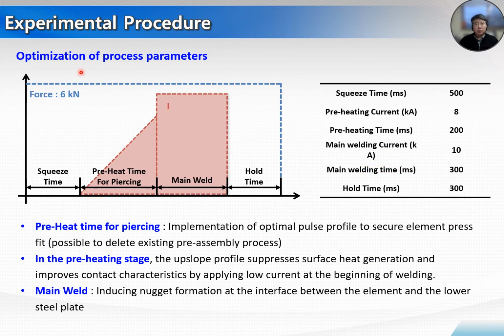For the experimental procedure for optimization of the process parameters, the preheating time for piercing, with implementation of the optimum pulse profile to secure element press fit, makes it possible to delete the existing pre-assembly processes. In the preheating stage, the upslope profile suppresses the surface heat generation and improves the contact characteristic by applying low current at the beginning of the welding. In main welding, nugget formation is induced at the interface between the element and lower steel plates. The following are the suggested welding process parameters.